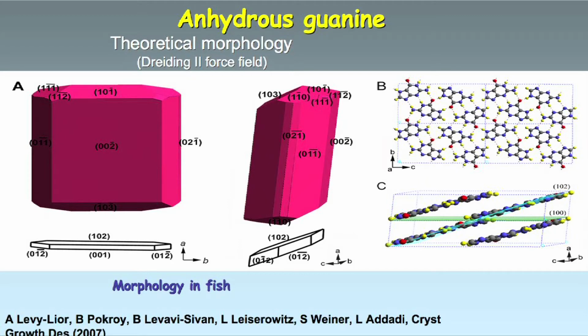And it is interesting also because if one calculates, as we did, the theoretical morphology, the morphology that we would expect these crystals to assume in a vacuum or in an appropriate environment, it is a prismatic morphology, where the face that is developed as a main face in the fish is in fact the less developed. So this means that the organism goes through a lot of pain in order to force these crystals to form as very thin plates, so that they can achieve a reflectance that is much higher than what would have otherwise been.